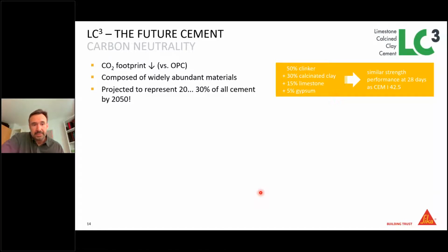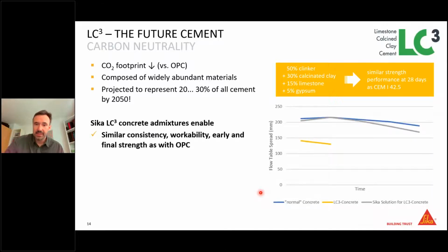And the challenge was that a concrete produced with such a cement has significantly weaker flow performance or consistency. So it was necessary to develop admixtures which allow the use of such a binder for a concrete with similar consistency, workability, early and final strength development as with OPC. So we believe, and not only us, that this is an upcoming technology and projected to represent 20 to 30% of all cements by 2050.